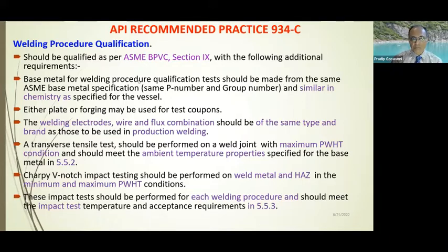The base metal for weld procedure qualification should have the same ASME base material specification, same P number, group number, and similar chemistry as specified for the vessel. That way, it is slightly lenient as compared to 934A. You may use either forging or plates as test coupons, and welding electrodes and flux combinations should be the same type and the same brand as used for the production welding.